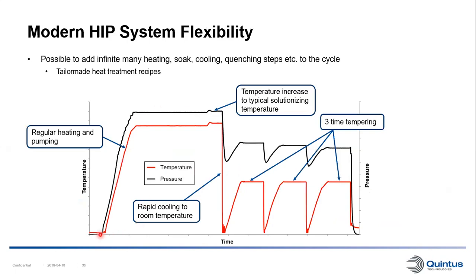So this is actual log data from a HIP cycle where we have combined the hipping and the hardening for a tool steel. So here we increase the temperature and the pressure as in a normal HIP cycle. We have our typical soak time, and then we increase the temperature just a little bit before quenching down to room temperature. And then here we have a 3-time tempering as well for this particular material. So it's a very flexible system to do heat treatments in.